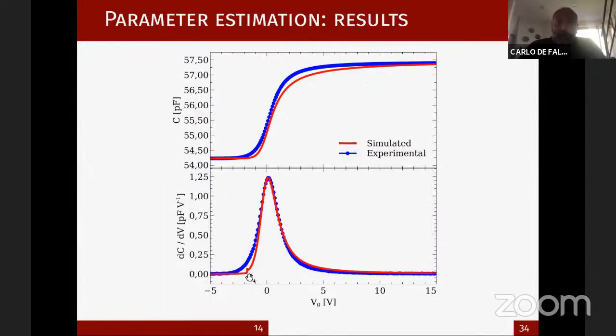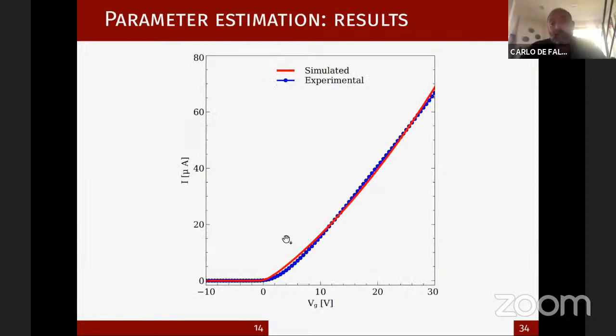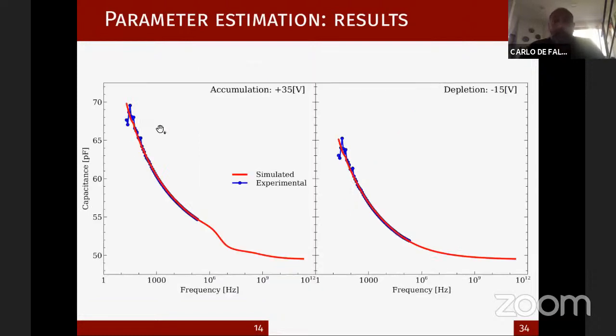And here you see how we compare simulated and measured capacitance of a FET device and use the simulation to fit the width of the density of states, and then how we use IV measurements. This is the so-called transfer characteristics of the device to fit the mobility and injection barrier of the device. And finally, after fitting the parameters, we simulate the frequency dependence of the capacitance and compare to measurements, and we find a very good match between the two. Now, 1D simulations are definitely not the interest for exascale simulation, so let's move on to the interesting part.